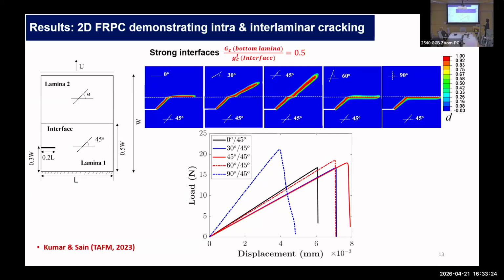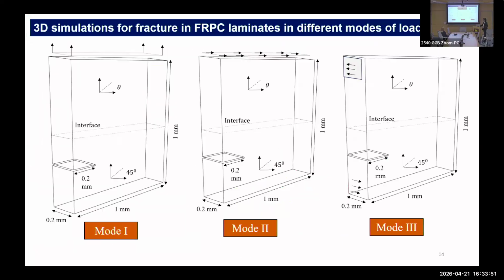And this one, 90 degree, 45 degree is the strongest one and the stiffest one, but brittler compared to the other cases. So if anyone is trying to design a composite where you want a predefined crack path, this is the way you want the cracks to maneuver. You can probably use one such model fairly easily and then design the layup, how you want your crack to propagate in a composite domain.